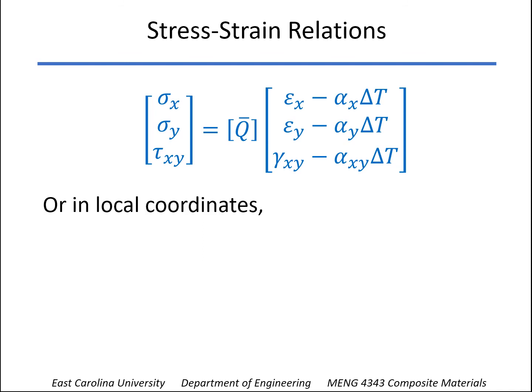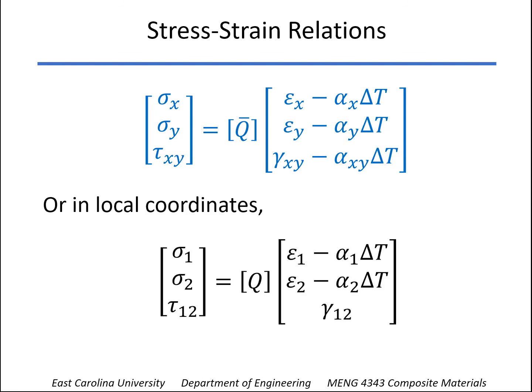So we can do that in local coordinates as well. We can have the stresses in the local coordinate system be equal to the Q matrix times the mechanical strains, but once again, take the total strains in the layer and subtract off the free thermal strains. And again, since there is no alpha 1, 2, then that becomes 0, so you don't subtract anything off of the shear strain gamma 1, 2.